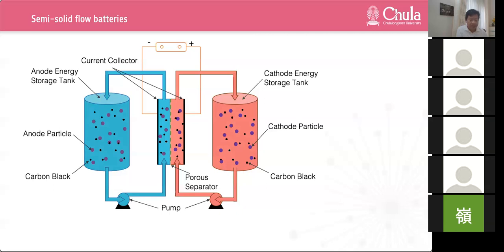Conductive electrolyte system cannot be used in multiple stacks because of the shunt current through the electrolyte connecting multiple series connected cells in a stack, driven by the voltage difference between the cells. In addition, the chemistry and the physical properties of the suspension need to be carefully controlled. A high solid loading is normally designed to achieve high energy, but the high suspension viscosity could contribute to pumping related energy loss. So we should think about it too. Right, pumping a liquid suspended with small particles will consume a lot of energy.